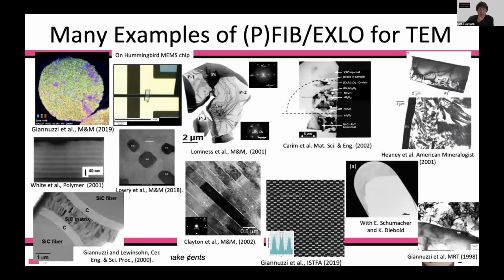We have been able to apply ex situ lift out techniques to a number of different specimens. Early on, we were interested in FIB milling different sample types, and now, of course, we can even use a plasma FIB for different samples. So anything from polymers to ceramics, metals, even hard biological type samples like bone. Here is an example of nacre, abalone, composites, thin films, etc. And they can be used for conventional TEM as well as high resolution TEM. So it was quite fortuitous that early on, when we were interested in applying FIB to TEM specimen prep, ex situ lift out also worked for a variety of samples.